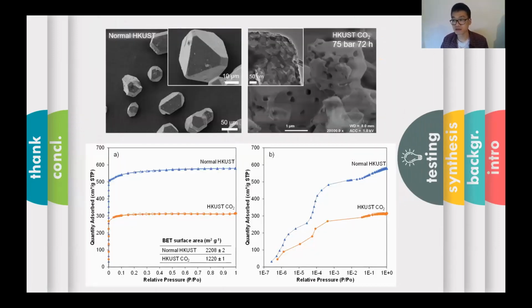To prove the benefit of introducing macropores in catalysis, we took the sample synthesized in CO2 at 75 bar and 72 hours to compare with the normal HKUST-1 with only micropore structures. The gas adsorption results show that the surface area of the CO2 sample is lower than the normal HKUST-1, which is due to the defects in the CO2 sample. Normally, a lower surface area will compromise catalytic activity, but we will see how these materials perform in the later slides. We also notice that the micropore structures of these materials are similar, which is confirmed by the similar pattern of the nitrogen isotherm at low pressures.